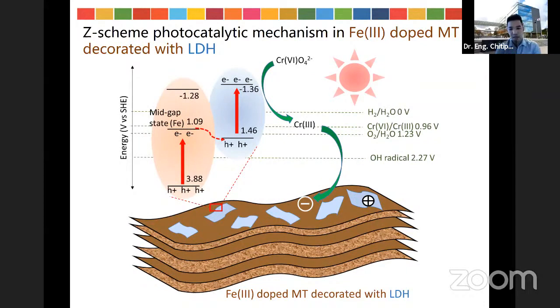So under light irradiation, the excited electrons are transferred to the valence band top of the layer double hydroxide, and the electrons are excited in the LDH and accumulate in the conduction band of the LDH. The hexavalent chromium can be reduced by reacting with the electrons in the conduction band of the titanium layer double hydroxide, or LDH material, in the blue side, to reduce the toxic form of chromium to a less toxic form, for example, chromium 3+. And some chromium 3+ might be adsorbed on the surface of the Montmorillonite because of the electrostatic interaction between the positively charged chromium species and the negatively charged Montmorillonite.